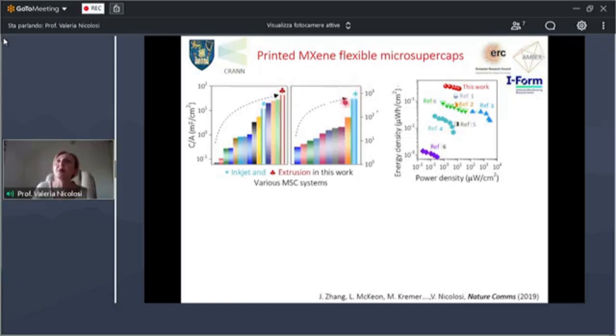If we compare their performance, here in red you have the performance of the extrusion printed supercaps, and here in blue the performance of the inkjet printed devices in terms of areal capacitance, as compared with a lot of literature out there, similar devices in terms of thickness, area printed, and things like that. You can see that these devices truly outperform anything that had been reported up to that stage in 2019 at least, but I think it's still quite a record.